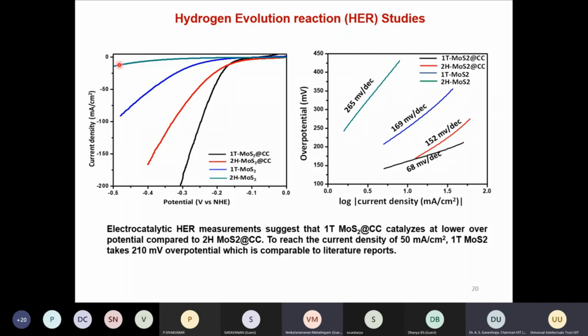Even they are not able to achieve this 10 milliampere per centimeter square. But what we can see here is that the 1T phase shows better activity. This is also reflected in the Tafel slope, where the overpotential is plotted against the log current density. What this value means is basically how much overpotential is needed to increase the current density by 10 times. This is one of the characteristic features which we measure to relate this material to other materials. So you can see that the 1T phase material shows only 68 millivolt per decade, whereas the other material shows a higher value.